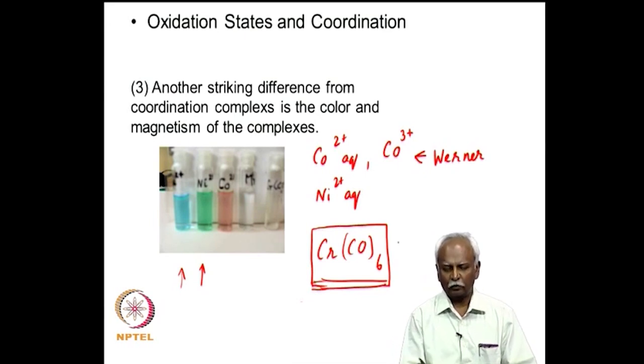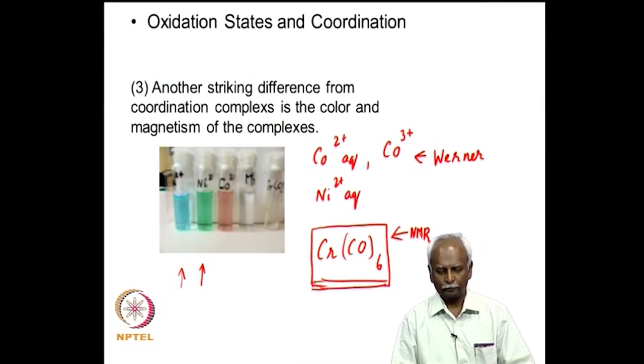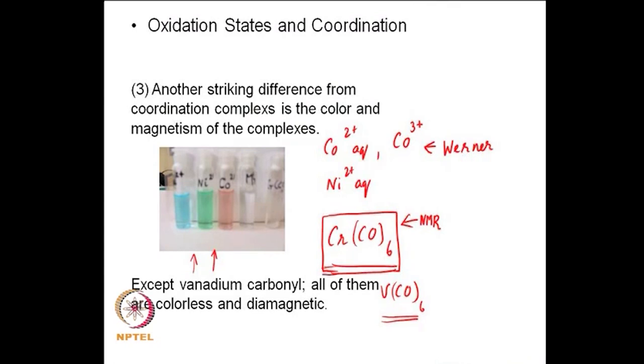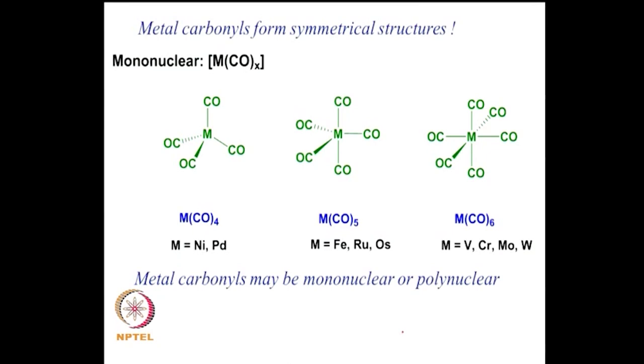This is a distinct advantage because you can carry out NMR spectroscopy of these complexes. NMR spectroscopy allows you to monitor these compounds in situ in a very easy fashion, and this advantage is not present for the Werner coordination chemistry that we encounter, where you have paramagnetic systems, and paramagnetic systems tend to destroy the NMR signals fairly easily. Vanadium carbonyl is an exception, because V(CO)6 can be generated, and if it is V(CO)6, it tends to be paramagnetic, it is not diamagnetic. So, this is one exception that we note. Okay. So, let us move on.